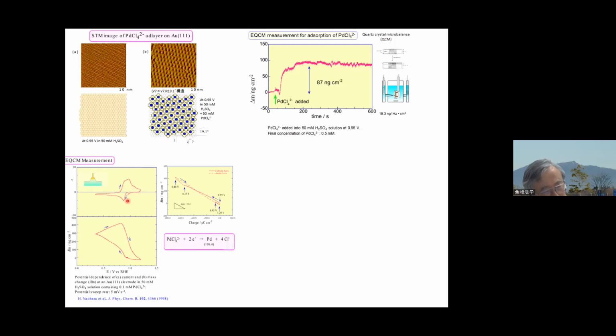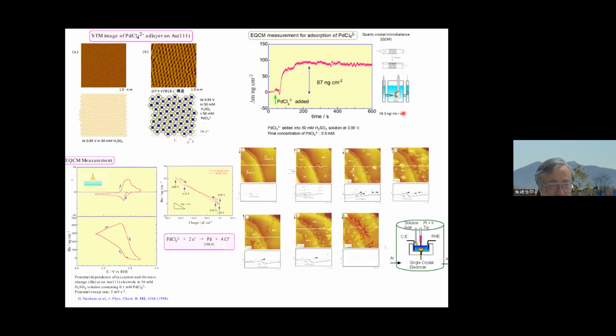Then we scan the potential negatively so that the palladium atoms adsorb on the surface. This is the cyclic voltammogram, and this is the weight change calculated from the frequency change. Then we integrated the charge and plotted it against the weight change, and it is linear. This is Faraday's law. The slope shows 53.2 grams per Faraday, which means two-electron deposition of palladium on the surface. So by doing this, you know the metal is deposited.